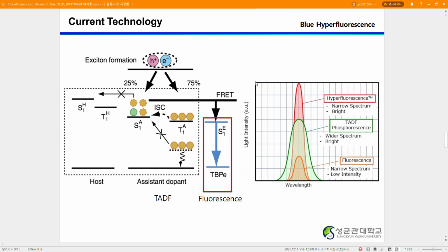This slide shows the hyperfluorescence OLED. The blue TADF OLEDs achieved high external quantum efficiency, but the spectrum of emission is relatively broad, which means color purity is bad. To solve this problem, the researchers developed a hyperfluorescence system in which TADF materials work as an assistant dopant to increase efficiency of transfer of exciton from assistant dopant to fluorescence emitter.